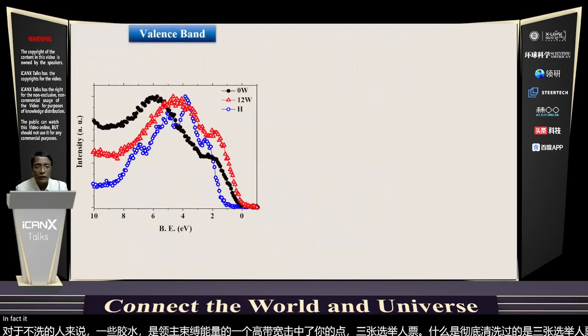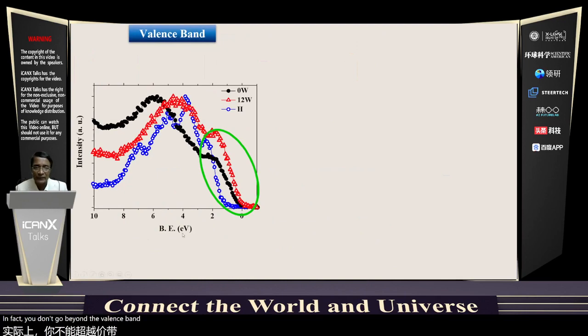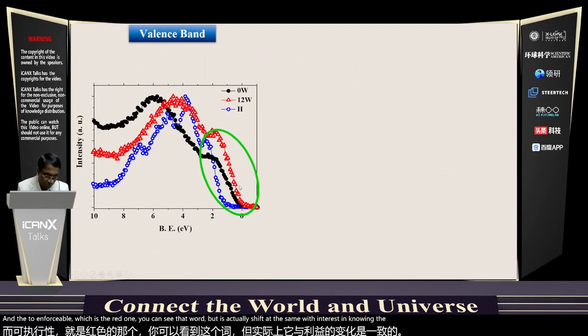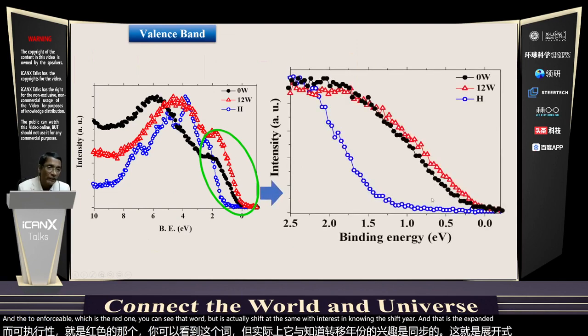In fact, it turns out even the valence band, and this is the valence band spectrum of the 0 watt sample, which is the black dots, and the 12 watt sample, which is the red one. You can see the 12 watt is actually shifted this way. We're interested in knowing the shift here, and that is the expanded form I've shown here. That shows about a 0.2, 0.3 electron volt shift in the leading edge.